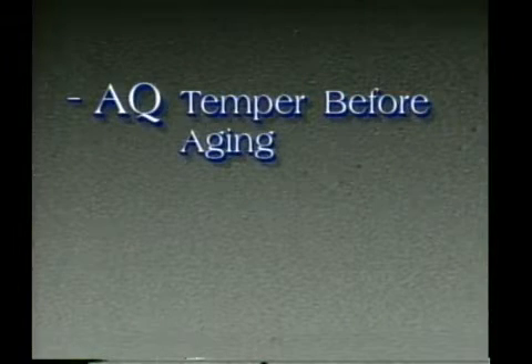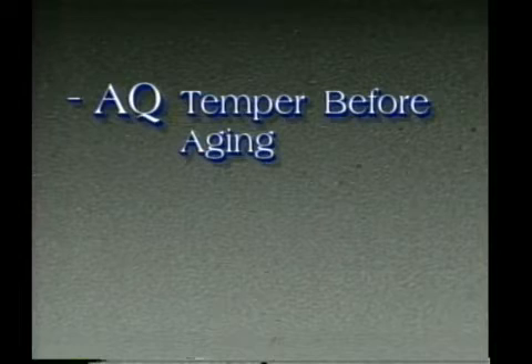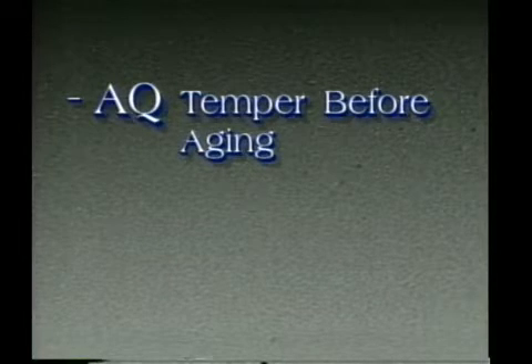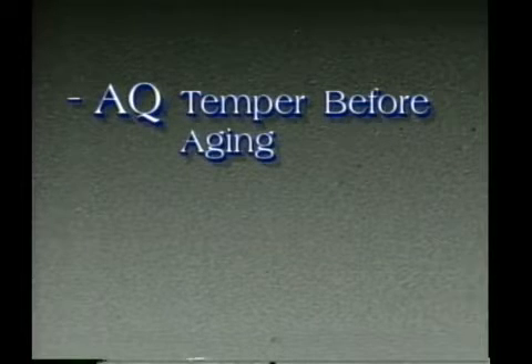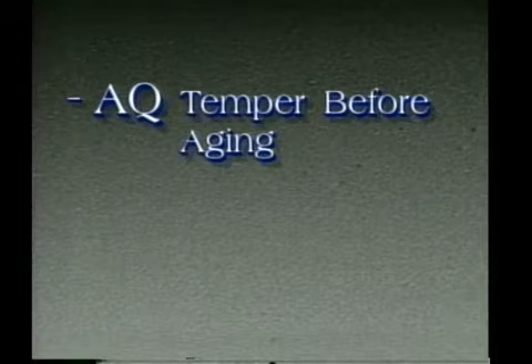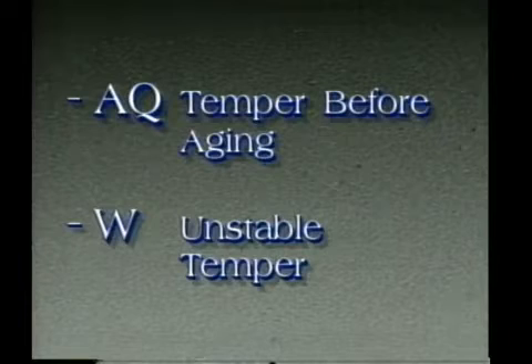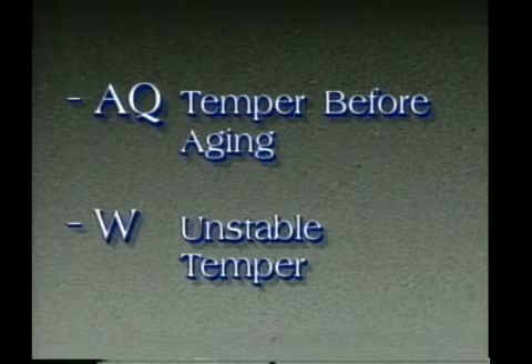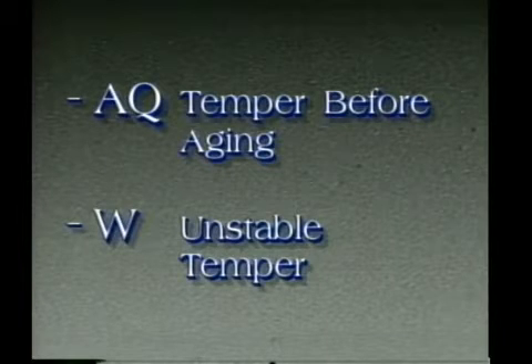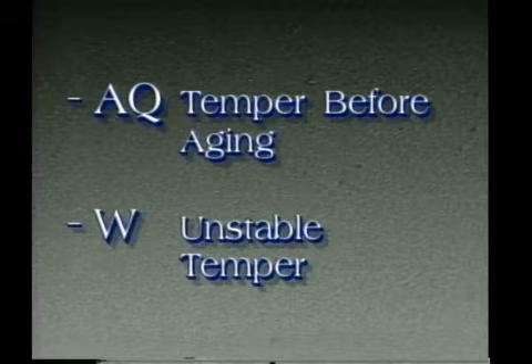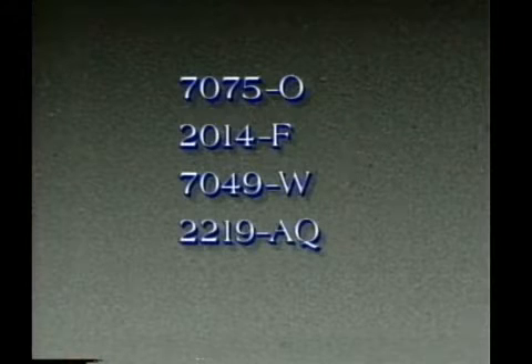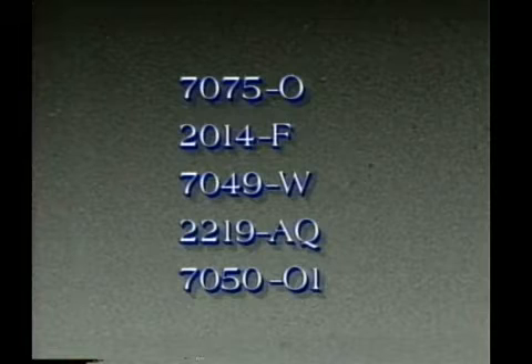In addition, there are two other tempers commonly used for identifying interim conditions in the heat treat plant. These are AQ, the temper formed immediately after quenching before any appreciable natural aging occurs. At room temperature, this temper lasts for about a half hour. Refrigeration at temperatures of 0 degrees Fahrenheit or lower can preserve this temper for up to many months. W, unstable temper, that is formed during the natural aging process. This temper exists as soon as significant aging starts after quenching and remains until no further natural aging continues. When those tempers are used, they appear as 7075O, 2014F, 7049W, 2219AQ, and 7050O1.